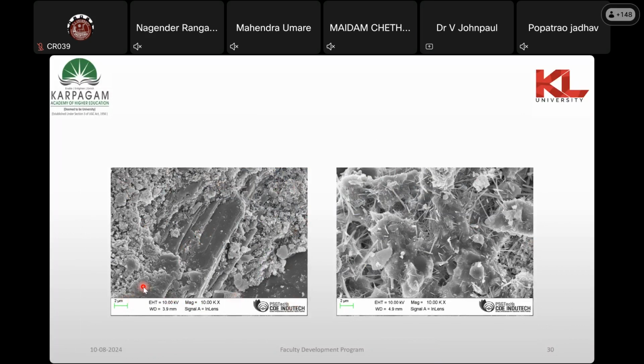normal, that is like if you take M20 with 1 is to 1.5 is to 3, fine aggregate, 3 part is coarse aggregate. Along with this is GGBS incorporated concrete. You can see the formation of ettringite. You can clearly see the formation of CSH. There is a close bonding between the paste and the aggregate which forms during the hydration process. In the long run, we can reduce the landfilling as well as the concrete production materials too.